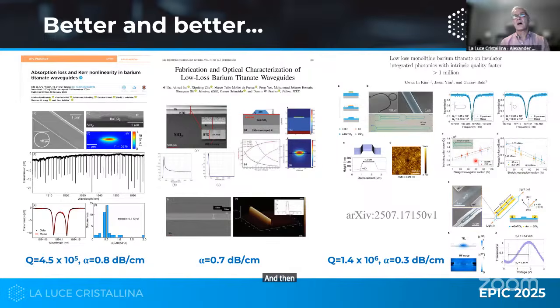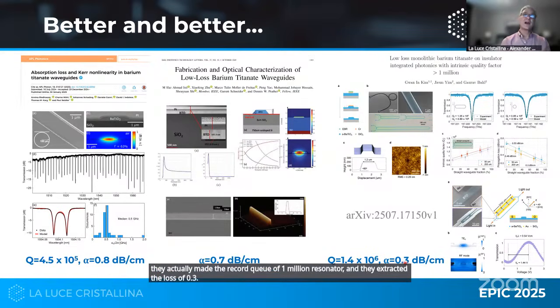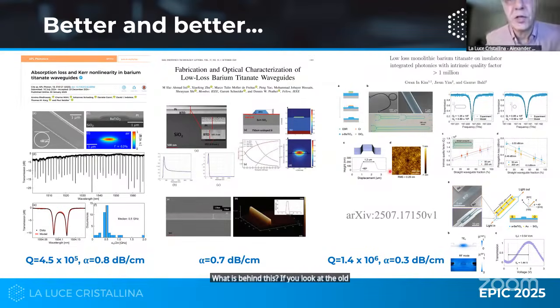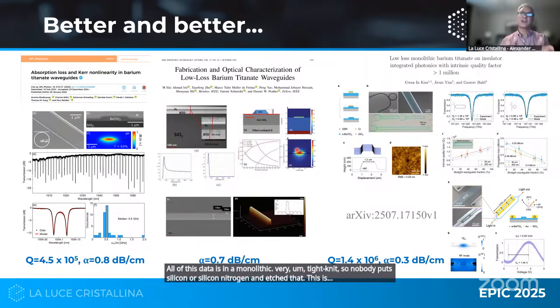And then this is the work on the right from University of Illinois in Champaign-Urbana. They actually made the record Q of 1 million resonator, and they extracted the loss of 0.3. What is behind this? If you look at the old literature, for example, the old IBM papers, the loss is much, much higher, on the order of like 40 dB. So what's the difference? All of this data is in the monolithic barium titanate. So nobody put silicon or silicon nitride and etched that. Guiding is done in barium titanate proper. And also most of them are done in barium titanate grown on large wafers.